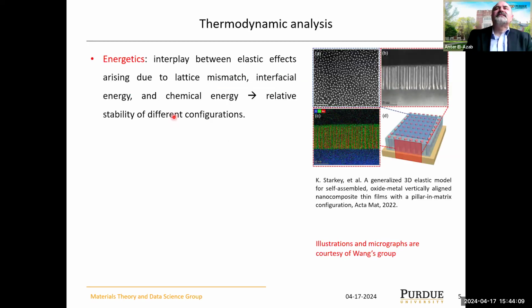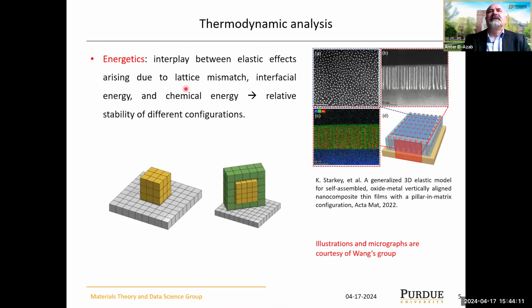In the energy business, we look at the interplay between elastic energy, interfacial energy, and chemical energy in these systems. The elastic energy arises from the fact that these things are made of multiple materials, gray, green, and gold here. And these multiple materials are crystalline, and they have different lattice parameters. So when you try to fit them together to form a composite material like this, you have to stretch one of them and compress the other in order to fit them together. That is called lattice mismatch.